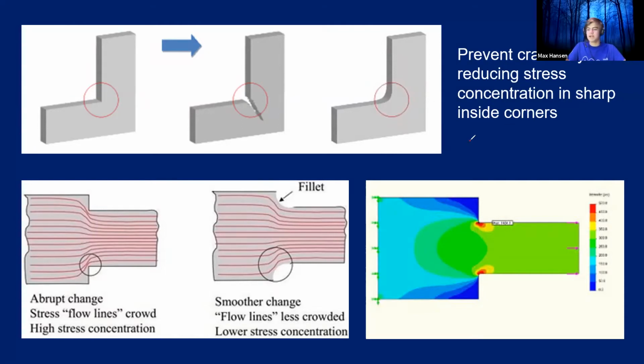And then this bottom right image here is actually a stress tester on the computer. So you can put in where you anchor the part and where the force goes. And as you can see, these sharp corners here are highlighted in red because they are very, very prone to breaking and are one of the highest stress areas on any part you can make.